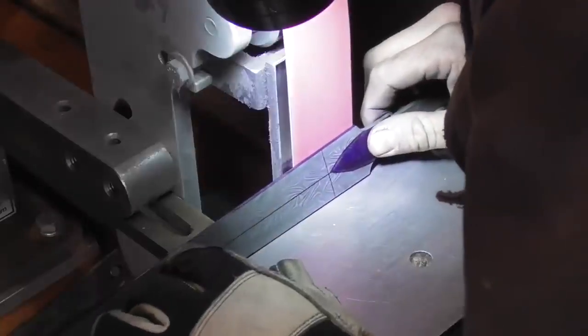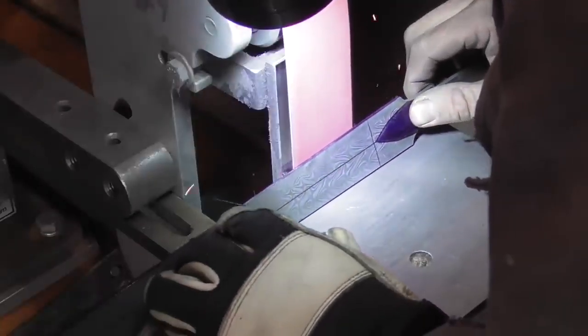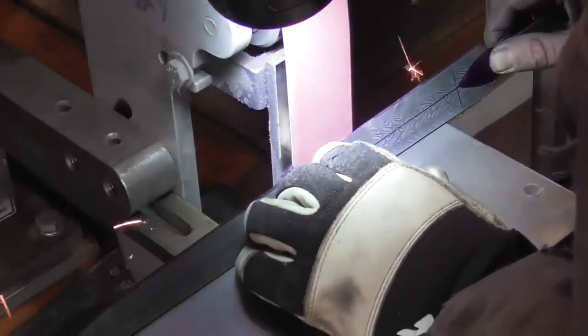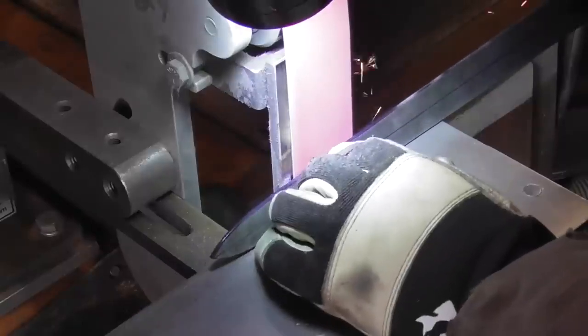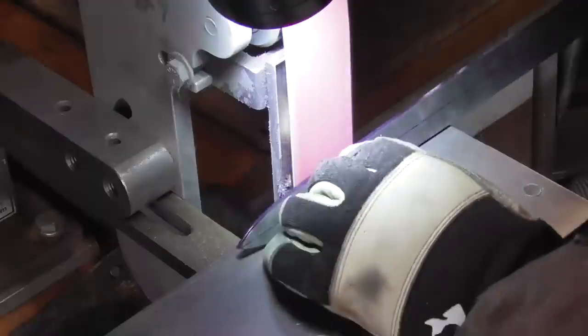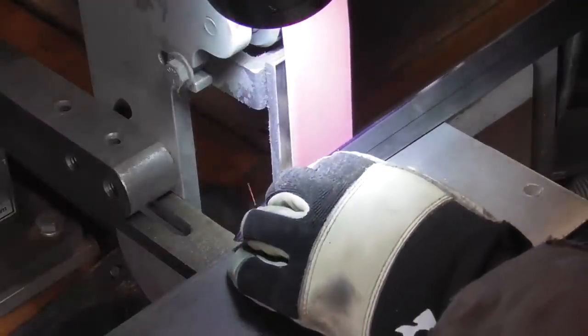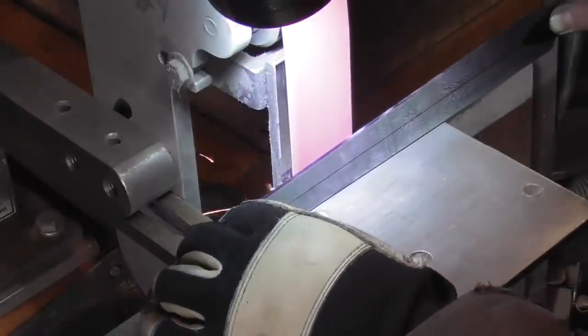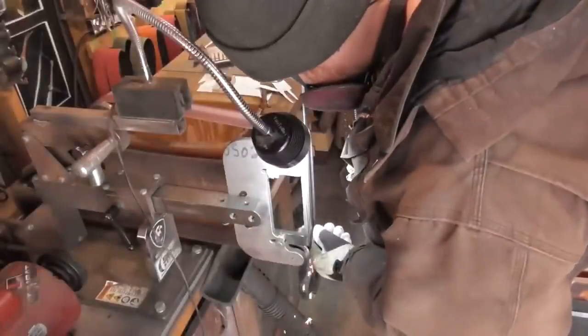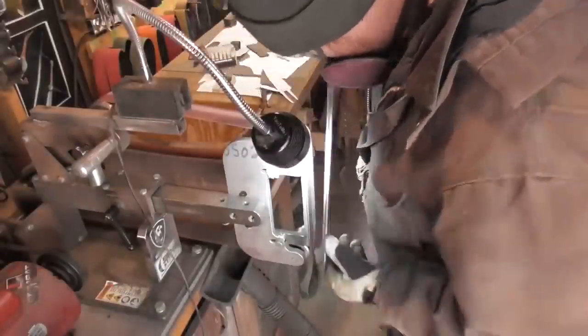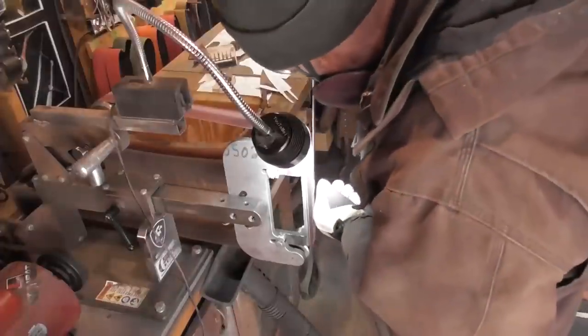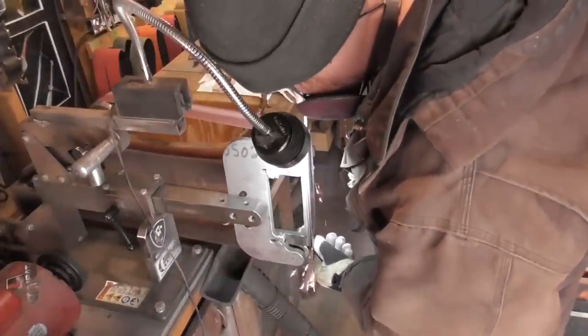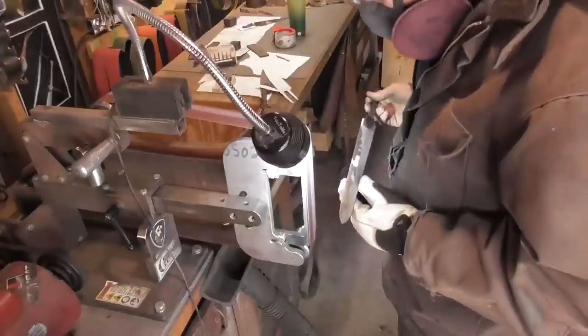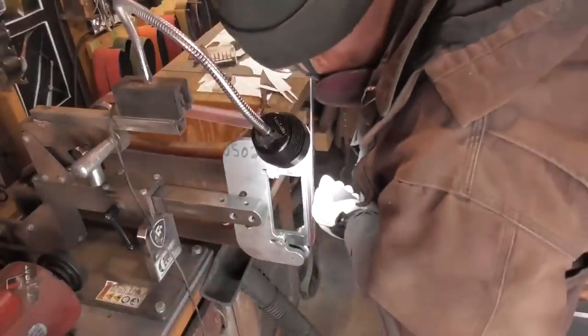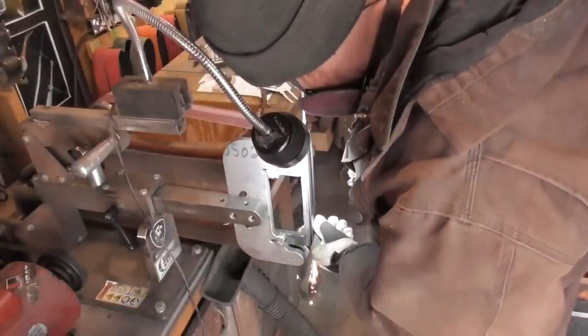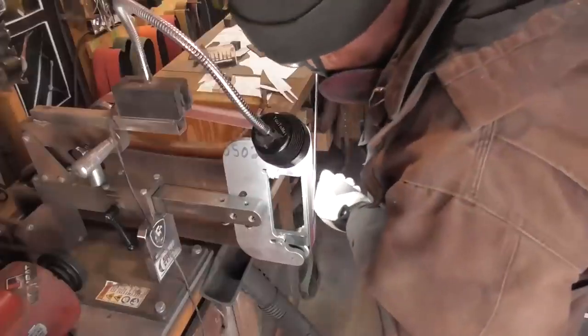Once I have my ricasso laid out, it's time to start actually grinding the bevels on the dagger. To begin with, I just grind down to the center line of the thickness of the dagger, and then once I get that established, I'm going to start slowly working back to where that center line is on the width. Once I have that ground, I go into the flat platen vertically to make sure that everything is as flat as it can be. You'll notice too, I'm staying away from that entire ricasso area. That's a big reason why I wanted to do that layout beforehand.